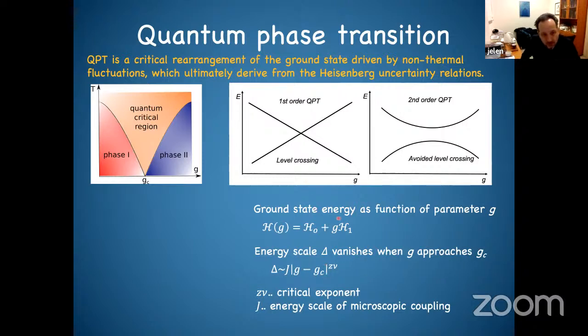And then when you go close to this G critical, you see that the band gap is vanishing. It should go to zero. And then again, you can build on top of that all this critical exponent theory and the scaling, etc. Now, why is this quantum phase transition important for us? Why should we care? Because typically it happens at zero temperature. But importantly, when you start to increase the temperature, above this critical point you go to what is called the quantum critical region.